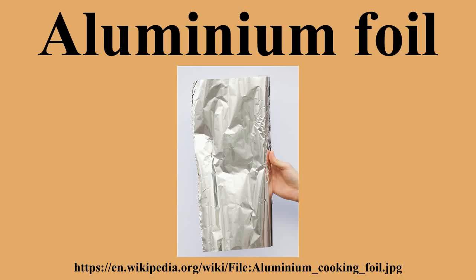The shielding effectiveness is dependent upon the skin depth. A field traveling through one skin depth will lose about 63% of its energy. Thin shields also have internal reflections that reduce the shielding effectiveness. For effective shielding from a magnetic field, the shield should be several skin depths thick. Aluminium foil is about 1 mil. A thickness of 10 mils offers less than 1 decibel of shielding at 1 kHz, about 8 decibels at 10 kHz, and about 25 decibels at 100 kHz.